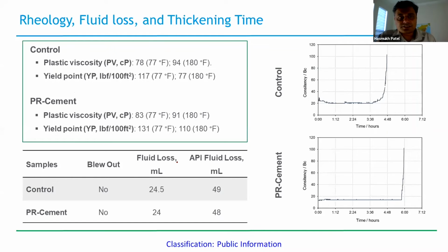Let's see what kind of properties 1% polyrotaxane provides. These are the typical rheology, fluid loss and thickening times that we measure for cementing materials, which shows that even if we add the polyrotaxane, we are not seeing much difference from typical cement formulations. Plastic viscosity gives information about the pumpability of the cement downhole. Yield point is very important because cement is a high-density material, so you need to make sure you have uniform density throughout the cement matrix. The higher the yield point, the better the uniformity of the density. We also have the fluid loss properties of the control and polyrotaxane cements, which tell us how the water is entrapped within the cement formulation throughout the curing process.